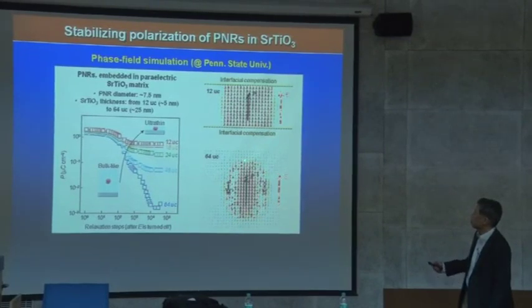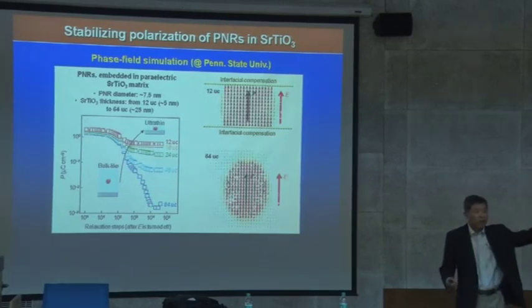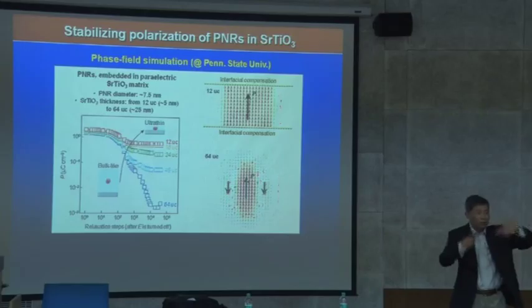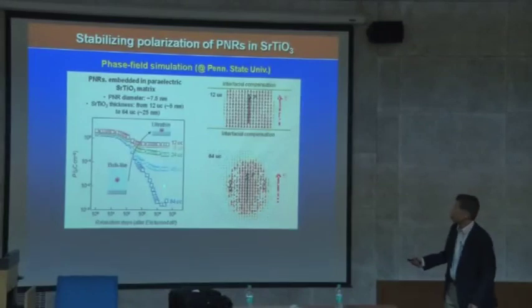and you switch the polarization, it just dies so quickly, very similar to what I showed in the PFM measurement previously, like the time scale measurement in the PRL paper. And then when you get thinner and thinner, at a certain point it doesn't die; it maintains this polarization for an infinite amount of time. Okay? So you have a crossover here: when you reduce the thickness, when you're touching the top and bottom electrode, this becomes a very stable ferroelectric. Okay? So that's our hypothesis.